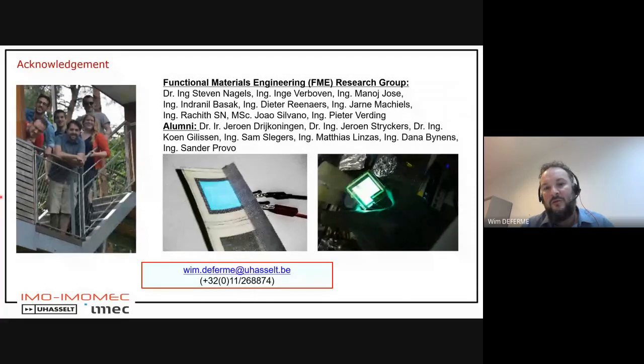Vida, you ask, how do you reduce the agglomeration of nanoparticles? If you mean agglomeration of nanoparticles when they are on the substrate, well, that's a good question. And I think that's a difficult task. Just by having specific nanoparticles without any linker or any chemical structure on top of the nanoparticle to prevent agglomeration, the only way to do that is to play with the ultrasonic spray coating parameters and to be able to deposit these nanoparticles in more or less a dry state onto the substrate.